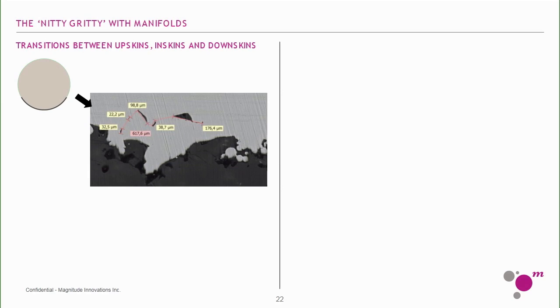Now, Velo 3D, for example, has a solution where they're building with 5-degree angles. The laser powder bed fusion area is focused right now on building something between 15 and 20 degrees. But when we talk about the angle, we have to talk about, is it possible to build? In other words, will the machine just crash? And then the other aspect is, is it actually going to meet our mechanical properties? In the case of the mechanical properties, 15 degrees is not really doable because you have these kinds of effects. So what we did is we redesigned the parameters so that we can remove this subsurface porosity.